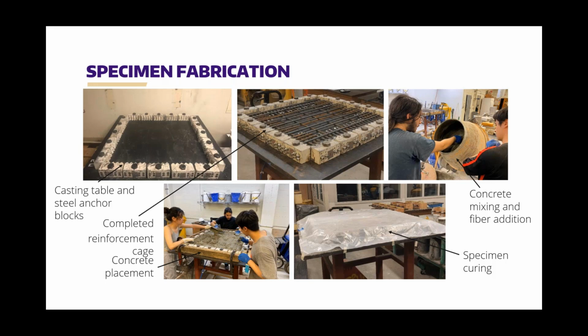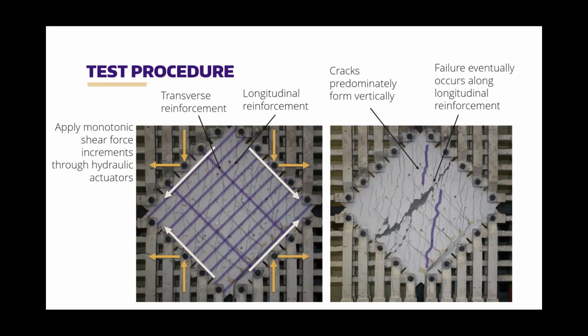You can see specimens were wet cured for 7 days with wet burlap and plastic, and then were tested after 28 days. So here's the test procedure.